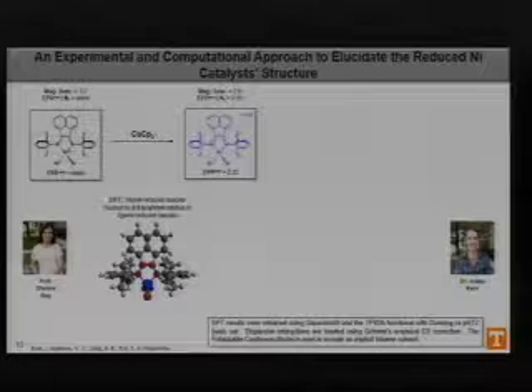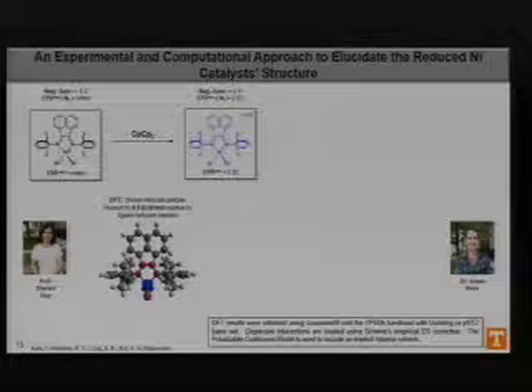Through using some experimental techniques, the EPR and the magnetic susceptibility, as well as DFT calculations, we found that once we added the electron to the system, we actually got an EPR of 2.3, and that agreed with the value calculated from the DFT calculations, which corresponds to nickel(I), as opposed to the ligand being delocalized through the backbone. Now, this was surprising because all of the other literature precedent had told us that it shouldn't have been this way. But then we thought, well, this isn't actually the active species anyway.